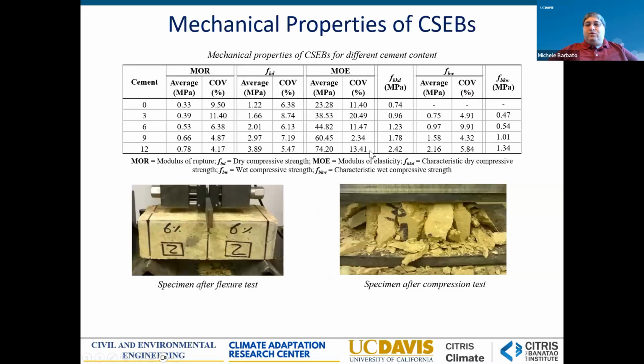So what we did, we used the cement to improve the mechanical strength and the durability of this material. And we started with the block made with only soil, and then we added cement, 3% of mass of the dry material, up to 12% cement. And then we performed the flexure tests and compression tests and durability tests, and the compression tests were performed both in dry conditions and in wet conditions.